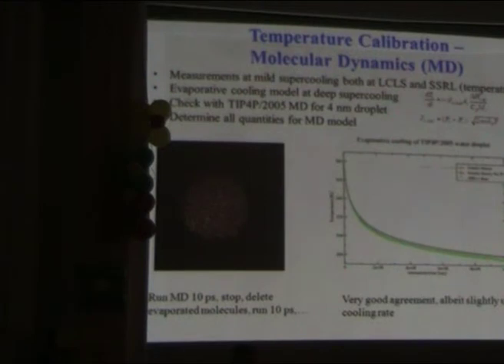Well, first of all, we need to verify the model. At the higher temperatures, the measurements can be done at the synchrotron, where we can measure the temperature. At the lower temperatures for the droplets, we need to use the Knudsen evaporative cooling model to derive the temperatures. We have a very good overlap between the directly measured temperatures and the Knudsen model in this region, but down here we turn to molecular dynamics simulations to verify the model. So what we do is we simulate a water droplet.